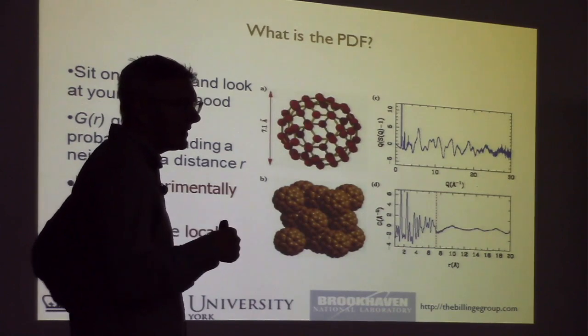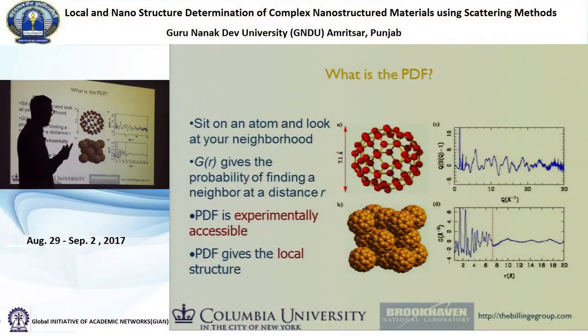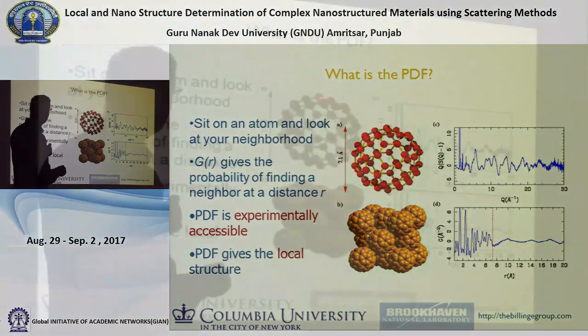And you see that first peak at 1.4 angstroms. It's the near neighbor peak. And the second peak is this one. And the third peak is diametrically across the hexagon. And then if you know what C60 is made of, it's made of hexagons and pentagons. So here's a pentagon here.